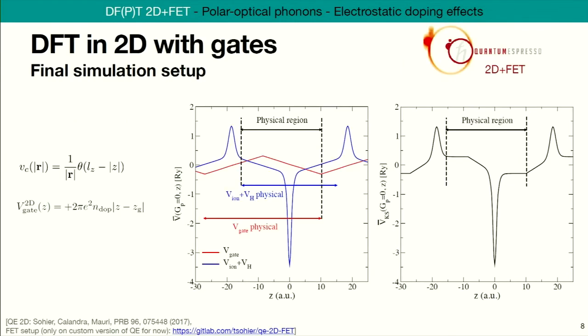But fortunately, it turns out that once you have implemented this cutoff and the proper 2D framework, the gates are relatively easy to implement. You don't have to worry about those periodic boundary conditions anymore. Everything kind of works out nicely. And this is what I try to show here. So first, let's look at this blue curve here. This is the potential generated by the charged material. So it is as you would expect. You have this dip that was there before. And because it's charged, you have this linear potential on the sides. This is what you would expect from a charged plane in vacuum.